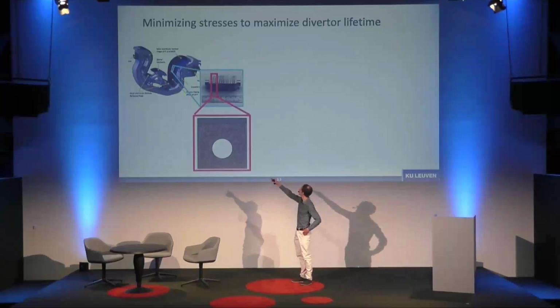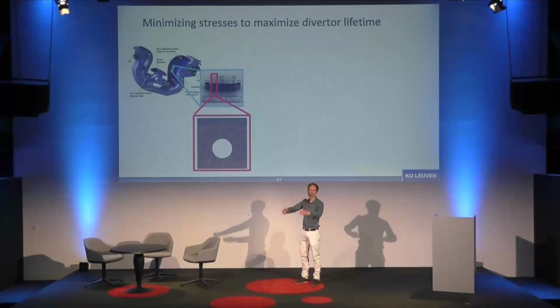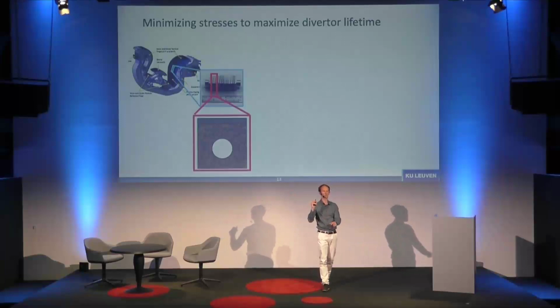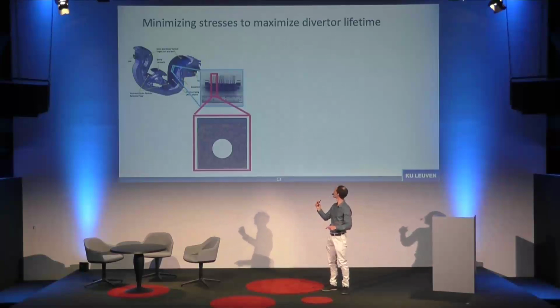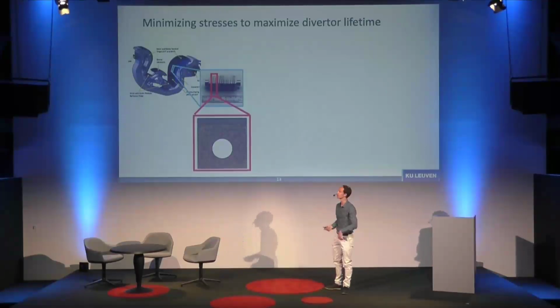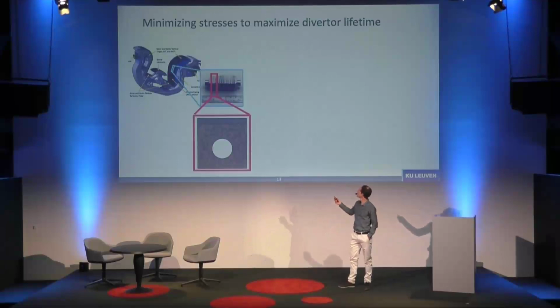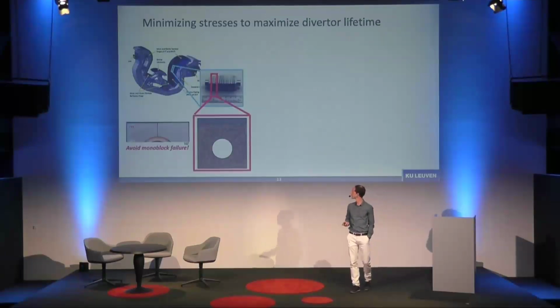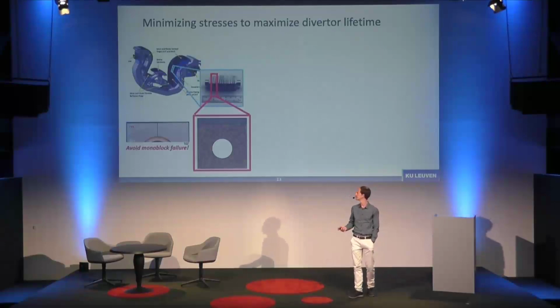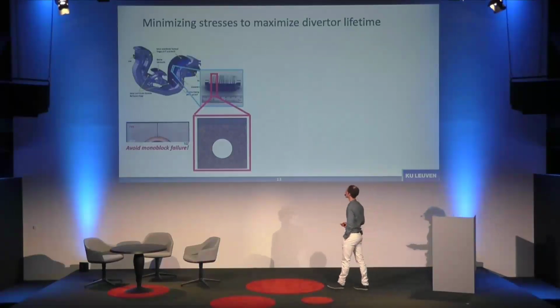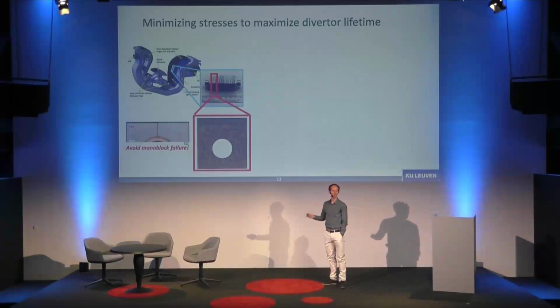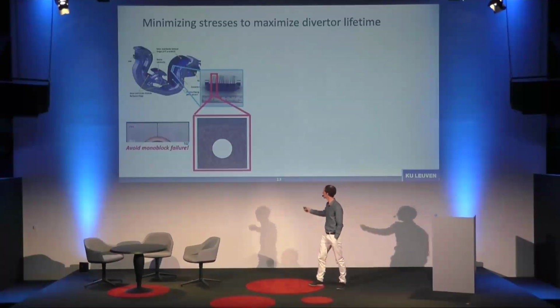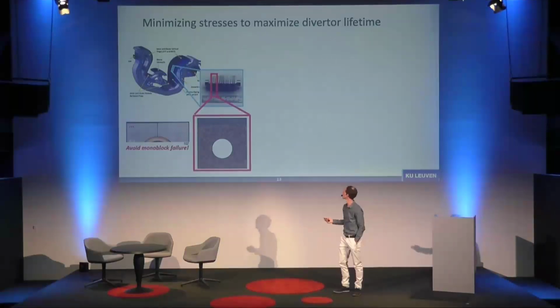So you see each of the divertor cassettes has a number of plasma-facing units, which are basically tubes with a coolant flowing through them, and on these tubes you have the individual monoblocks. And so if you're not careful with your monoblocks, they can crack if they're loaded too heavily. And so why does this happen? Well, you have a lot of thermal stresses in these components, and especially if you have material interfaces, you can get local stress concentrations, which can lead to cracking.